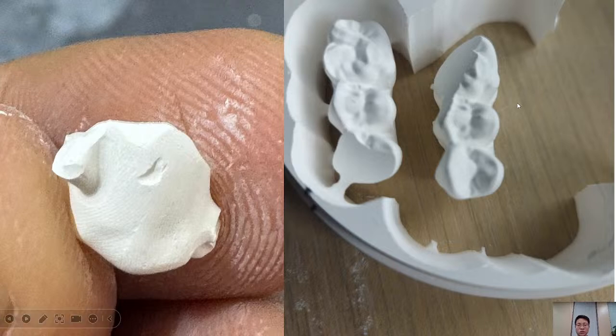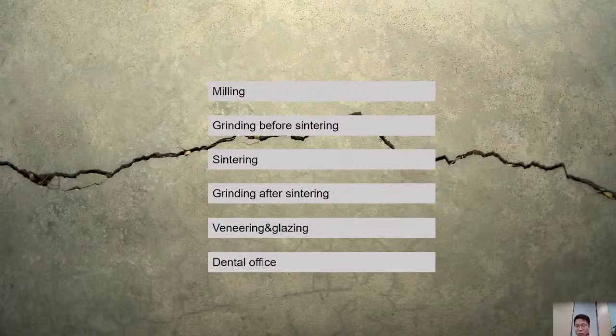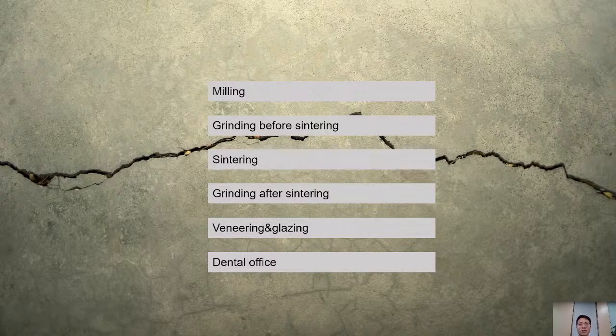And here are two cases which had crack problems during sintering. For the left one, we can see a surface crack, and the margin area is also not so good. The right case has a very flat crack like this. Okay, so what do we need to do if we meet a crack problem? We know a crack problem can happen at every step from milling to finishing. Even sometimes when it's in the patient's mouth, it will crack. So what should we do if we have a crack problem?